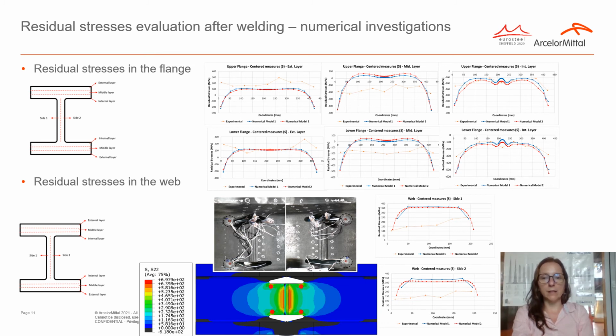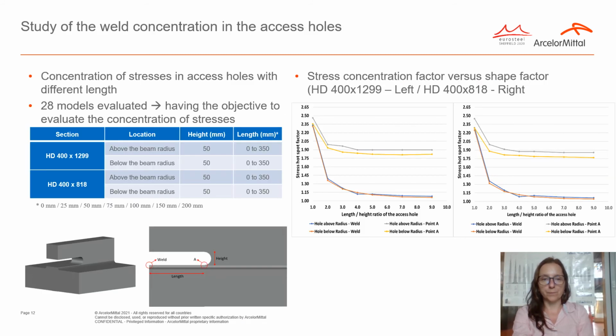In the access hole region, you can see in the upper image the position of the rosette, which is at the extremity of the access hole, and then in the lower image you can see that the peak was not obtained in the same position where the rosette was placed. So there was a difference in the experimental and numerical values between these 2 points.